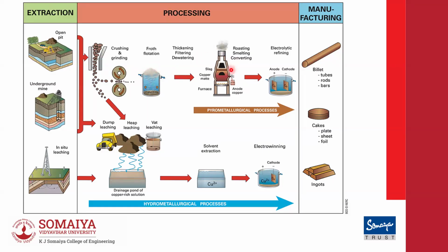This is then skimmed, and then I can either use a traditional roasting smelting process. Here I'm saying smelting, which means melting along with chemical reactions. I can form slag and matte. Sometimes I use the flash technique, which is a different technique. And then from here, the copper matte, which is again enriched with a good amount of copper in it, I use electrolysis to further purify the copper and obtain it in different forms. I have another route which looks at the liquid. So I can have extraction processes and electrowinning to give me the final product.